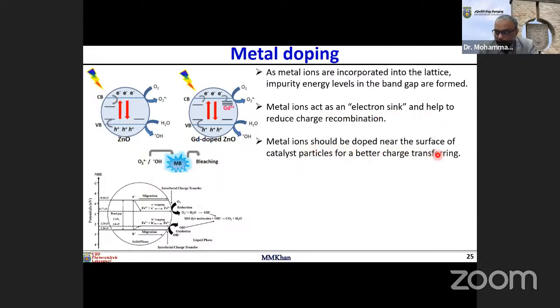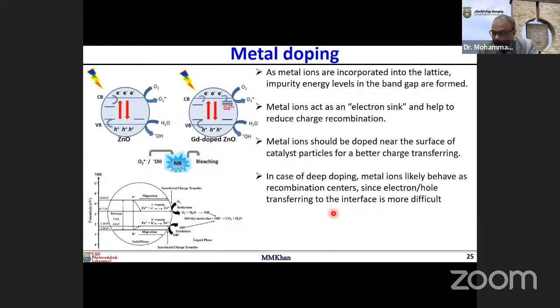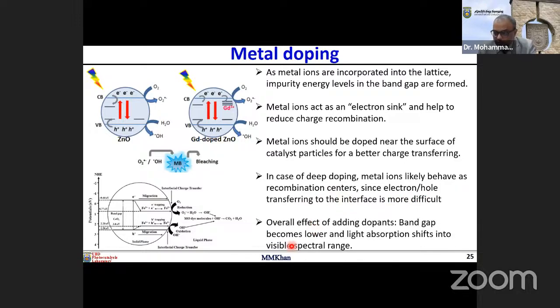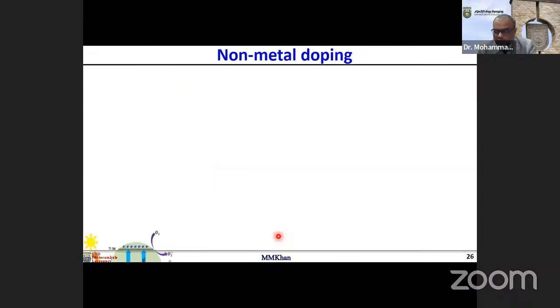Metal ions should be doped near the surface of the catalyst particle for better charge transfer. In the case of deep doping, metal ions likely behave as recombination centers, since electron-hole transfer to the interface is more difficult. Overall, the effect of adding dopants is that the band gap becomes lower and light absorption shifts to the visible spectral range. That is important here, because if your material has a wide band gap, it is very, very difficult, because you have to work with UV light, which is harmful.